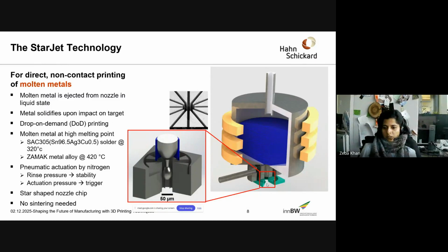it prevents this molten metal from quick oxidation, because if molten metal would come into contact with oxygen, you would have a very thin layer of oxide created immediately on top of it, and this then creeps into the inside of the material, ruining the material's conductivity. So in order to prevent such an act, we also have this nitrogen gas flow from the side of the Starjet printer. All in all, we have a good amount of material profile that we can print, and also the types of printing that we can do.